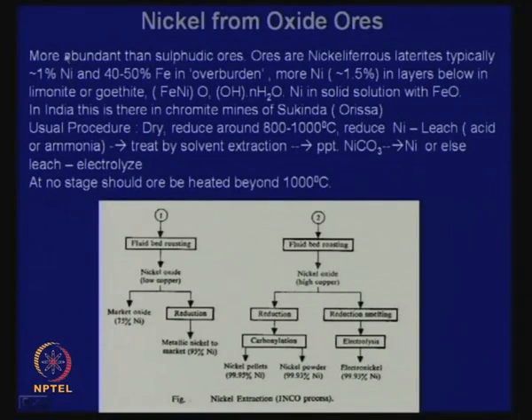Now, the oxide ores are much more abundant than the sulfidic ores. And the oxidic ores are called nickeliferous laterites, means they are associated with iron oxide deposits, typically containing 1% nickel and 40 to 50% iron in overburden, means in the top layers. There can be more nickel in layers below, and typically this kind of a composition we can expect, where nickel is in solid solution with FeO. In India, this is there in chromite mines of Sukinda.